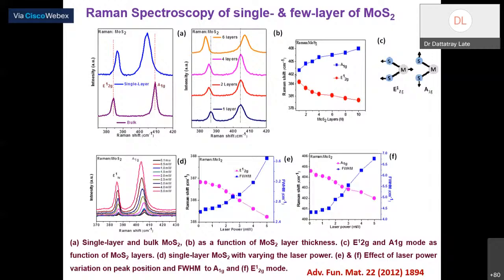You can see, as you change the number of layers, the Raman spectroscopy of bulk MoS2 and single layers gives you basically two peaks. The first is because of the E1 2G mode, where the molybdenum atoms move in one direction and the sulfur atoms move in the opposite direction. You can see that here at the extreme right corner. In the other case, the A1G mode, the molybdenum is at a stable position and the sulfur atoms are moving in opposite directions. So when the laser is shining, the atoms start vibrating and this gives you these two particular vibration modes.